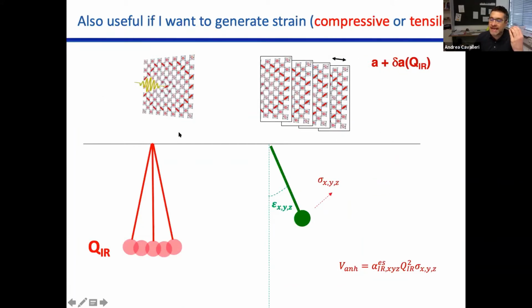By the same token, I can exploit couplings in which this particular excitation couples to strain, therefore changing the volume of the material. But what I was trying to say is that normally if I shine a laser pulse onto a material, what I will only be able to do is to increase the volume of the material and therefore generate what I would call tensile strain, so strain that enhances the lattice constant. But by choice of certain protocols, I can also create compressive strains and play with strain. I will make only one example of an interesting effect.